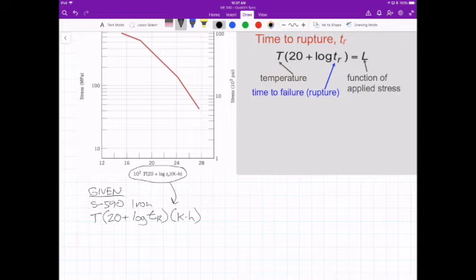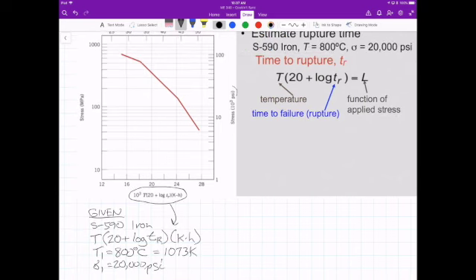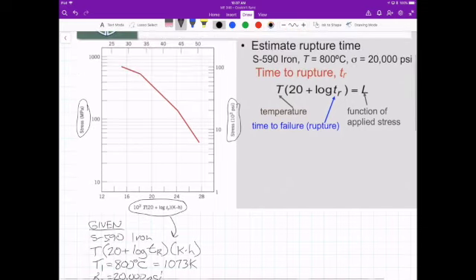Okay. Temperature given was 800 degrees C, which is 1073 Kelvin, right? So I'm converting that over. We're given a stress of 20,000 psi. We don't have to convert this to megapascals because it's already labeled on the y-axis on the right side. The left side is megapascals, so it basically converts for us.